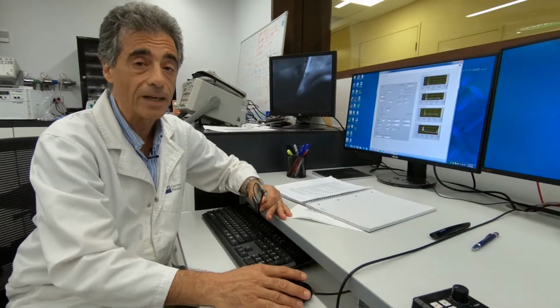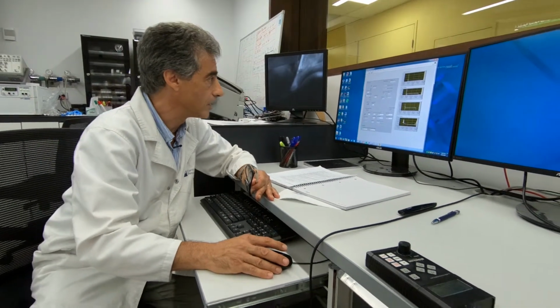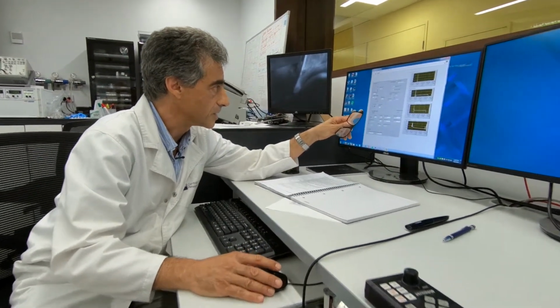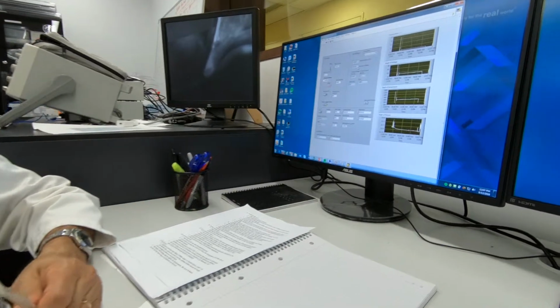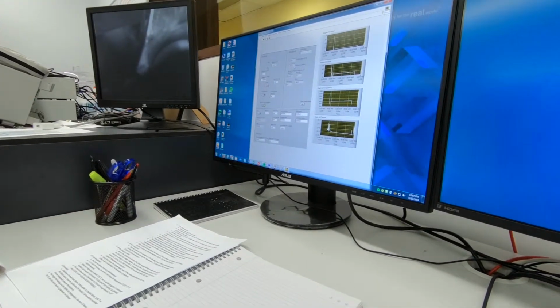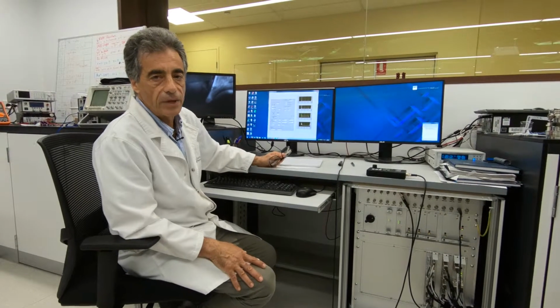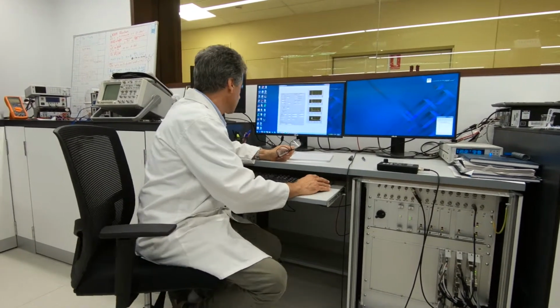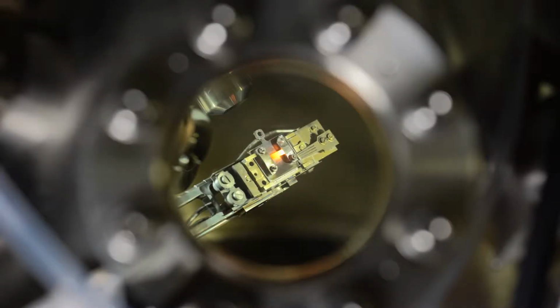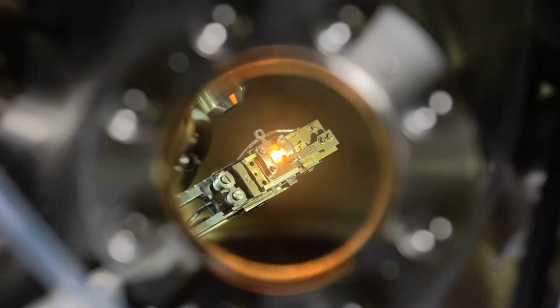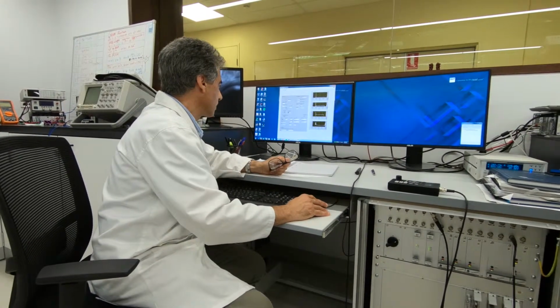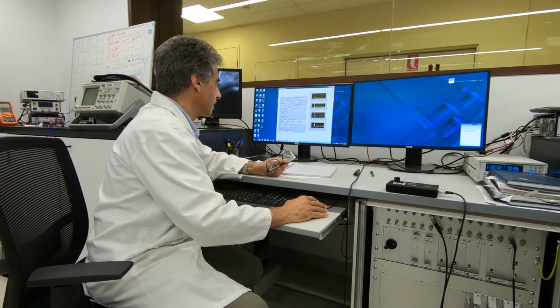We need to keep an eye on the gauge all the time, that is represented here, in order to avoid any contamination during the formation of graphene. And now we can see how the graphene grows. Let us start increasing the temperature to a value that brings the sample to 1,200 degrees. Once we are nearly there, we set the desired current, 1,250, and we activate the PID.